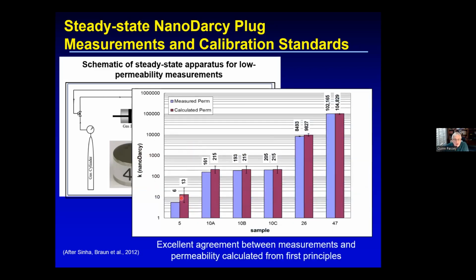And so here, we had a sample that we did here. This was calculated from the diameter of the capillary pressure within this fake core plug. The measurements that we got were about 6 versus 13. This is nanodarcy, unbelievable stuff. At the high end, we can measure 100,000 nanodarcies.